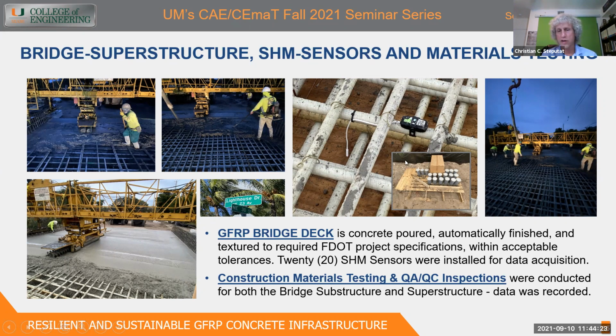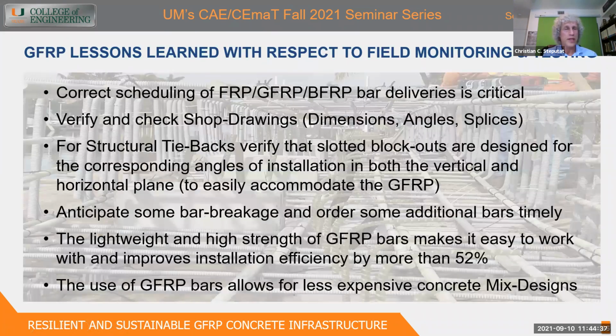By having these for 64 and 67 days, with my cell phone, I could just go there and get all the data, knew what strength is at what temperature, knew what area was hot, which one was not, where there was more wind circulation on the outer edges. And that was meant to look at crack propagation later to determine a little bit more reliability issues.